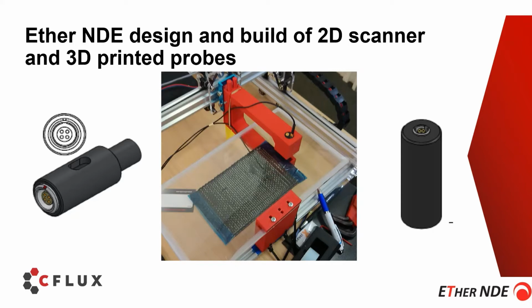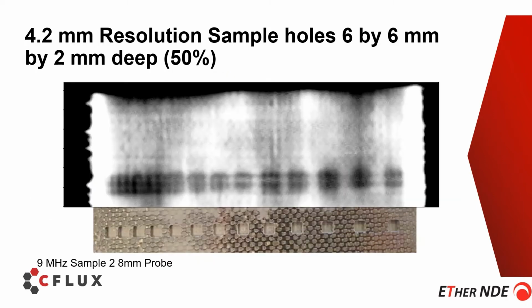Here we see some fabric, but we also mainly did the solid material. This scan shows results taken with through transmission on a 4.2mm thick sample with 6x6mm holes, 2mm deep, so 50%. We used through transmission system 9 MHz probes with 8mm diameter, and that's what the results show. The smallest gap we can see here is roughly 1mm, around about this part here.